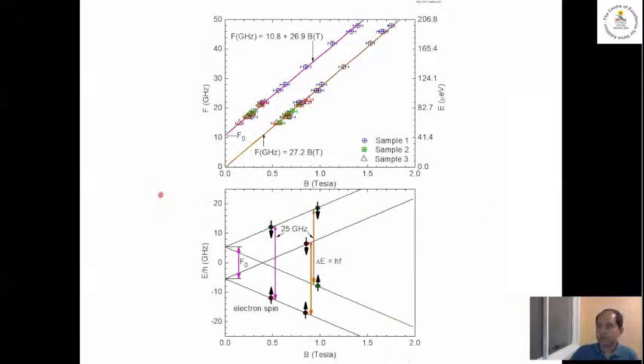So, let's summarize what we're saying here. This orange line over here corresponds to the usual spin resonance kind of transitions, but there's one with each sublattice. And then the purple line over here, which has some finite splitting at zero magnetic field, corresponds to this kind of transition. Even at zero field, you have finite splitting. So from this intercept here, we can get the splitting energy, 40 micro electron volts. And that's what we call a sublattice splitting.